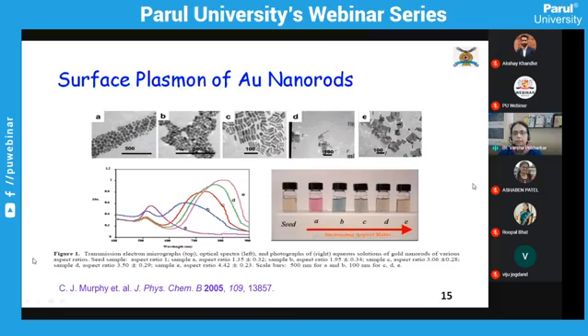If the particle is in the form of a rod-shaped particle, then depending upon its aspect ratio, as the aspect ratio increases, again you will see that there is a shift in the wavelength. So in the case of gold nanorods, there are two lambda max that are observed. One is observed typically around 520, and the higher one, the longitudinal plasmon band, is observed above 650 nanometers. So that is how a typical surface plasmon band will look in case the particle is in the shape of a rod.